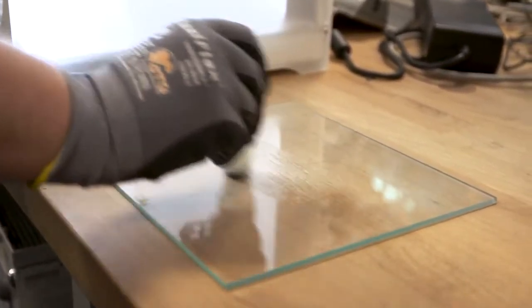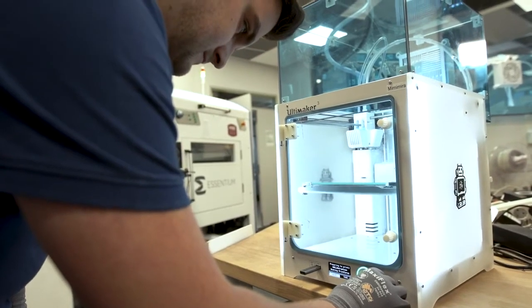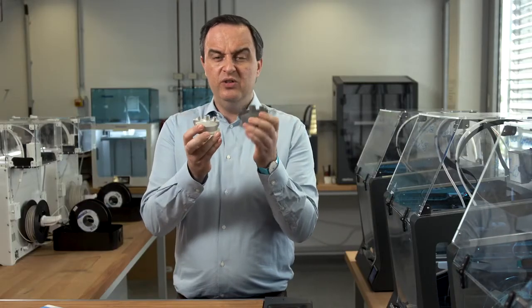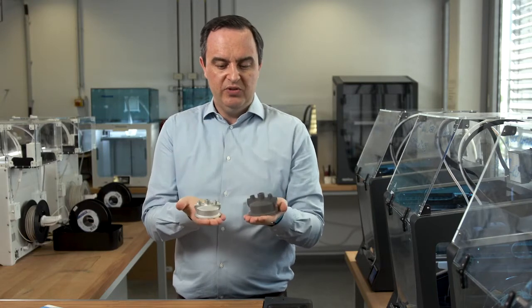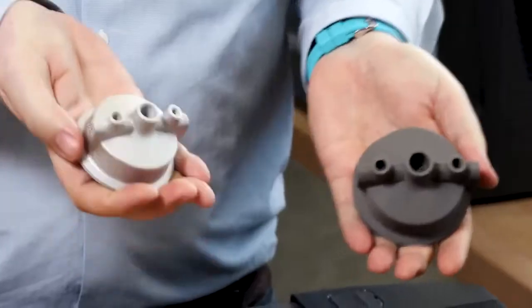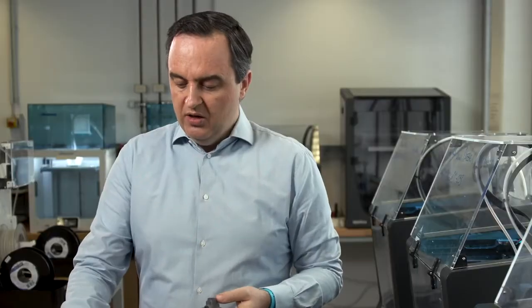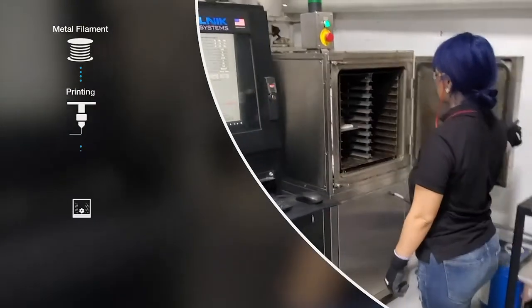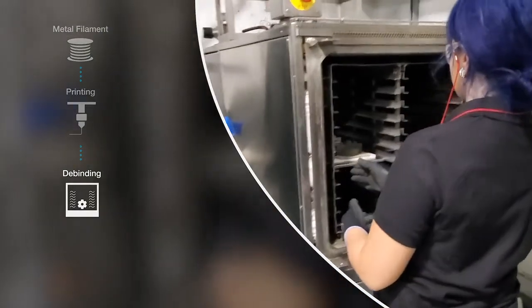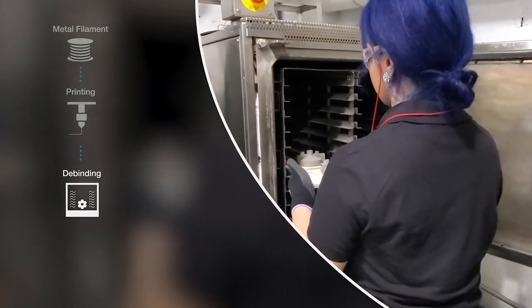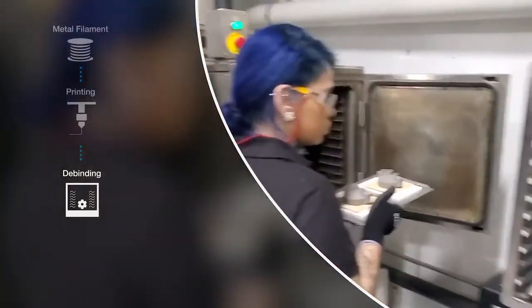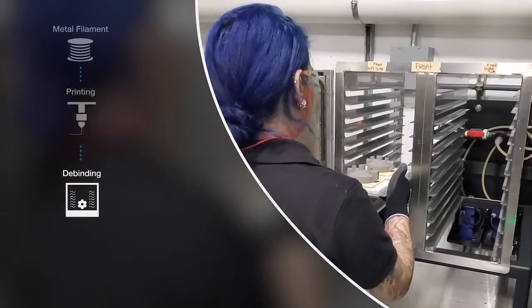Now you've printed your part, and you can see you basically want to go from our green part down to our metal part. And as you can see, there's that shrinkage we talked about, 20% in Z and about 16% in X and Y. So in order to get 316L to be fully metal material, when you're done with it, you have to remove the binder used, the organic compounds we use to bind the metal parts together. And that's done in a thermochemical process called catalytic debinding. Now, catalytic debinding, put simply, is just removing the non-metal parts and then, in the sintering process, combining the metal parts into one solid part.